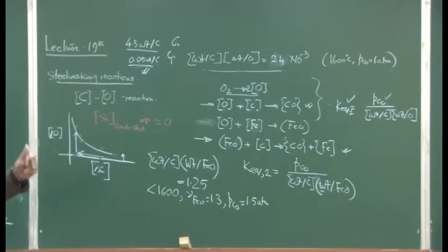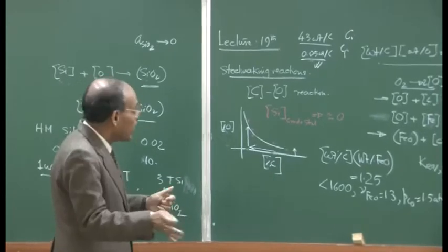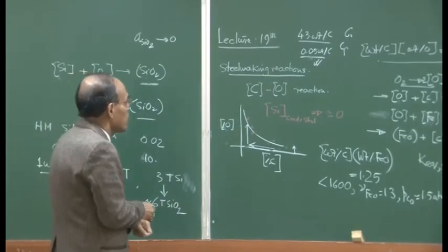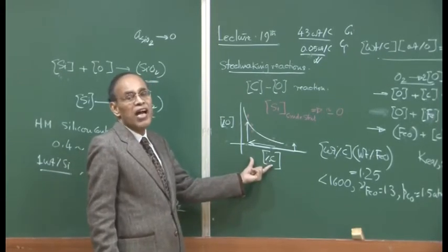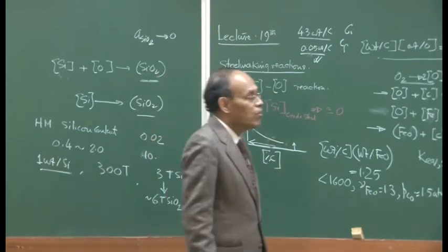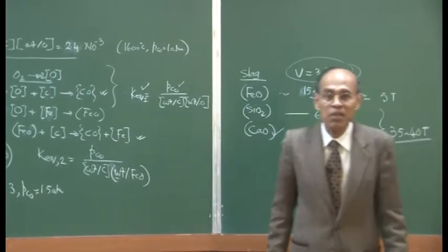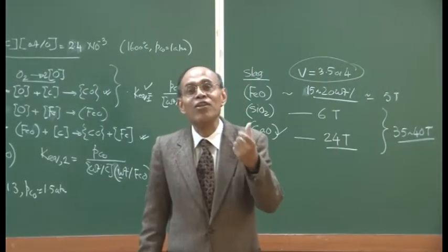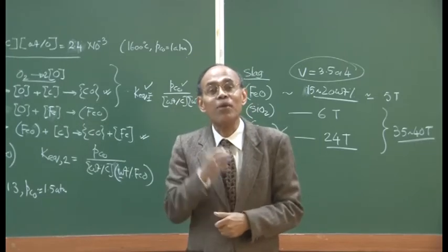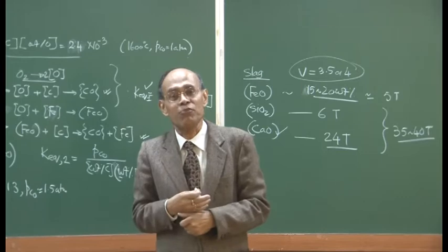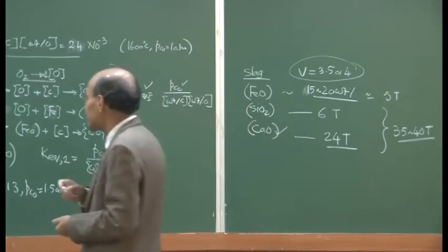There is a steady decarbonization period, as we will study, and then following the steady decarbonization period, towards the end, the decarbonization rate falls. But it is very rapid decarb: you can take 200, 300 tons and drive out, with 4% carbon, 4 tons of carbon in every 100 tons. So, if you talk about a 300 ton converter, you have 12 tons of carbon, and that 12 tons of carbon you will be able to drive out in 30 to 45 minutes of blowing time. So, you can imagine that the rate of decarbonization really is enormous. We will deal with all these things in greater detail.